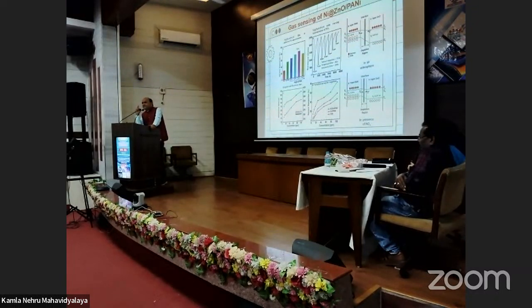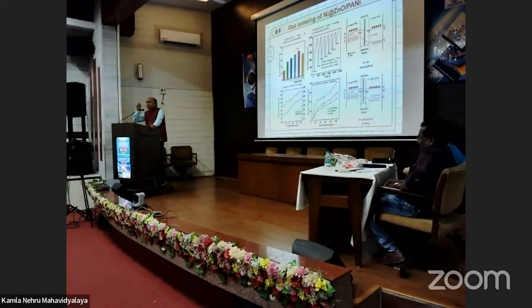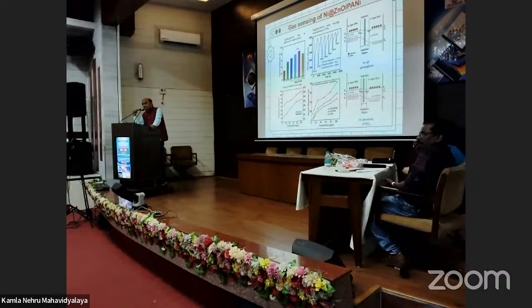What is the sensing? When we start to pass the gas, initially when the gas is in, there is an increase in the resistance, and when the material reaches saturation, the resistance seems to be constant, and as we start degassing, the resistance goes on decreasing. Means gas is in, resistance is increasing. When the saturation level is reached, the resistance is constant, and when gas is out, the resistance goes on decreasing.